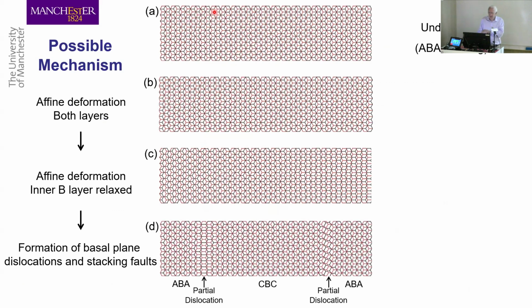And this is a schematic view of the different layers. So graphene has what's known as ABA Bernal stacking. You have A layers and B layers, and they are on top of each other. I'll call the A layer black and the B layer red. And you can see that normally, undeformed, they just sit on top of each other. But when you deform it, lots of things can happen. The layers can start to slide over each other, and you can get either affine deformation or non-affine deformation, or even the formation of partial dislocations and stacking faults, ABA, CBC, ABA, and partial dislocations. It turns out that, first of all, Bernal stacking is retained.